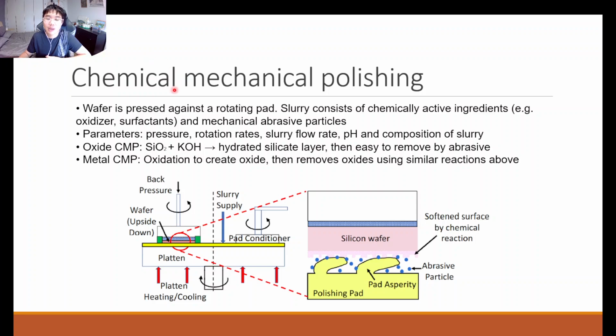So why is this called chemical mechanical polishing, right? It's because not only is there mechanical removal of your material through abrasion, but there's also a chemical reaction that often occurs that makes it easier for you to remove material off your wafer surface. For example, if we are removing a primarily oxide layer, we add KOH, potassium hydroxide, to a slurry, which reacts with SiO2 to form a silicate salt, and this hydrated silicate layer is then easily removed by the abrasive because it has a certain solubility in the solution.